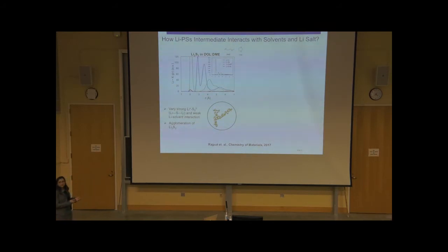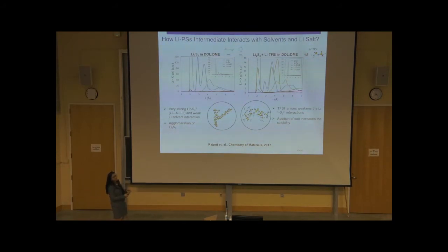And lithium salt also plays an important role in determining the solubility of this polysulfide species. So we added LiTFSI in Li2S2-DOL-DME mixture, keeping everything else the same, and we observed a significant change in the solvation structure. We still observed very strong interaction between lithium and polysulfide, but there's also increased interaction between lithium and solvent molecules. So again, what's happening here is these TFSI anions compete with polysulfide species to interact with lithium, and they break this strong lithium polysulfide network and allow more solvent molecules to interact with lithium. And by doing that, they can increase the solubility of lithium polysulfide species.